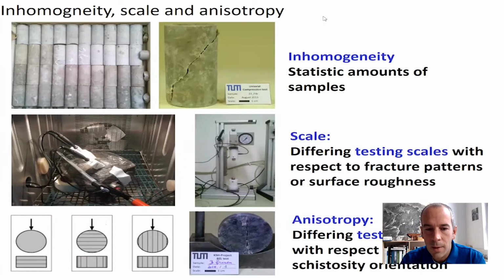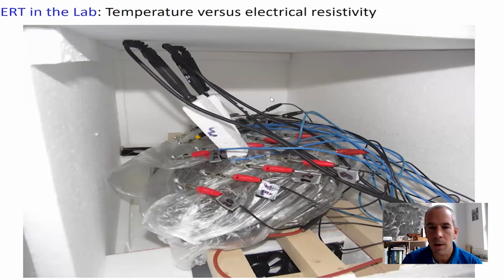Okay, if we do that, we have an issue because we don't use engineering materials, we use real materials. So if we want to find a difference between frozen and unfrozen strength of Zugspitze limestone, we can't take 5 samples or 10. We have to take something like 80 or 90. So that puts a lot of work on us, and you see how they break. So we need statistical amounts of samples. We need to change the scale to see how important fracture patterns are. And for rocks that have an anisotropic pattern, we have to test from different directions to see if that applies to all directions. Let's quickly go over the physical changes rocks undergo when they start to thaw.